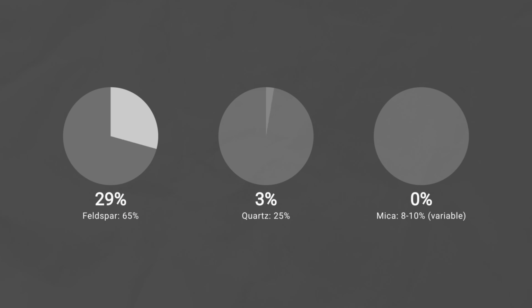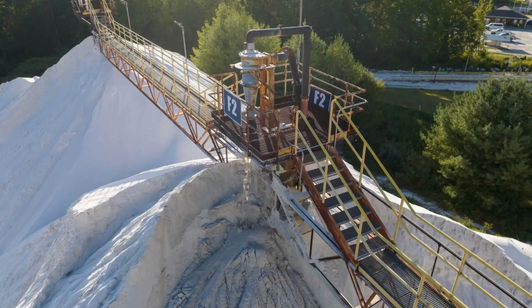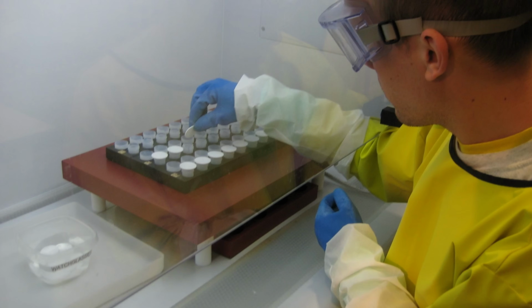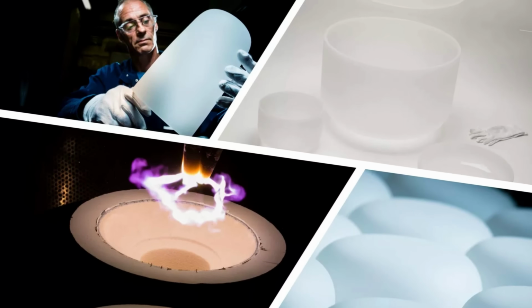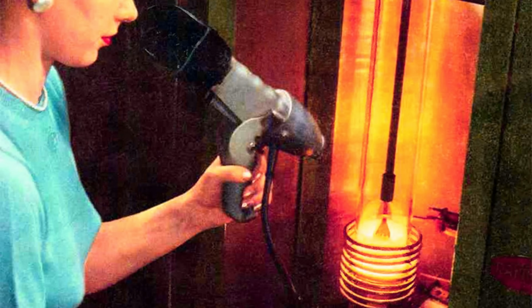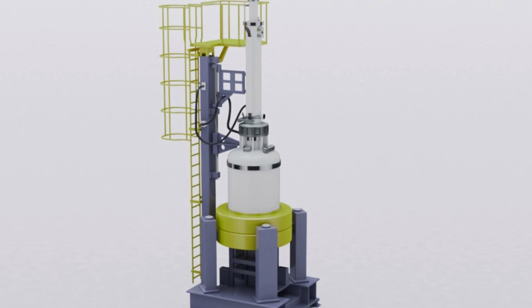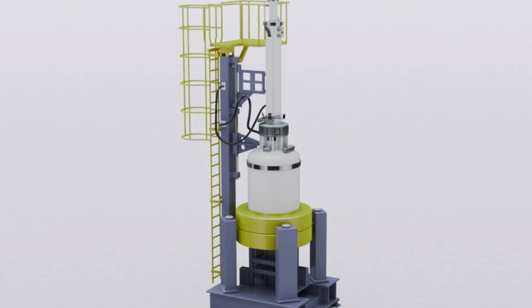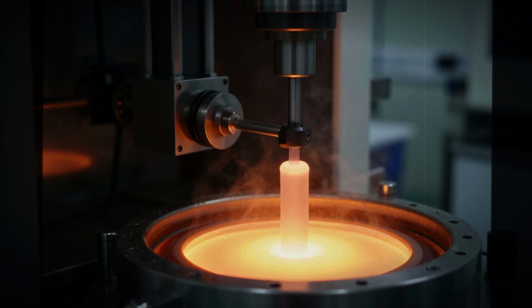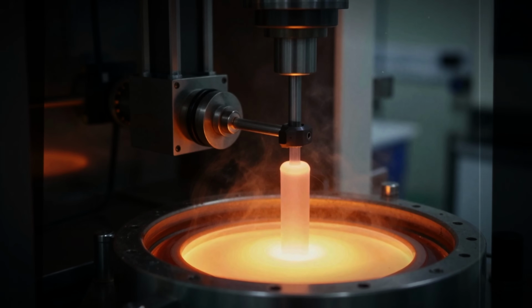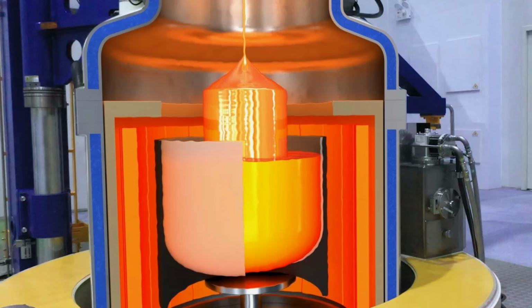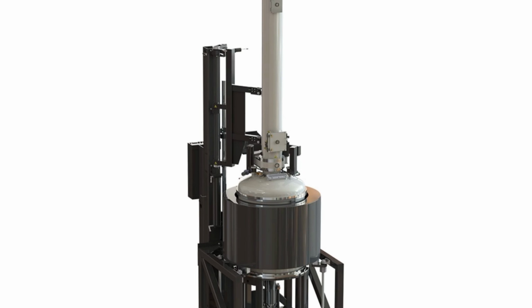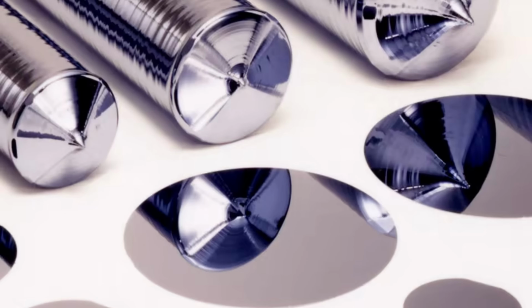The rock composition in the district is roughly 65% feldspar, 25% quartz, and 8 to 10% mica. When the feldspar is extracted, the quartz is separated out. The purest grades, the ones with 80 impurities per billion, are processed into fused quartz and shaped into crucibles. Those crucibles are used in the Czochralski process, the dominant method for producing single crystal silicon. A seed crystal is dipped into molten silicon held inside a spruce pine quartz crucible, then slowly drawn upward while rotating. The silicon crystallizes around the seed as it rises, forming an ingot, a pure cylinder of silicon sometimes a meter long. That ingot is sliced into wafers thinner than a credit card.